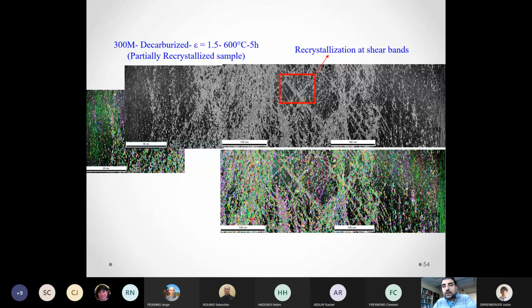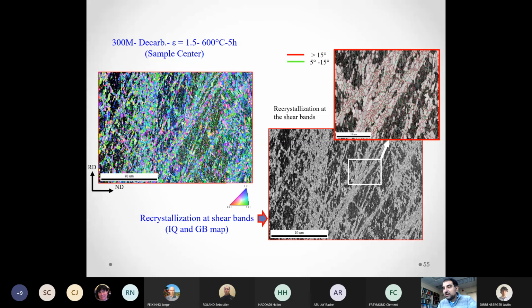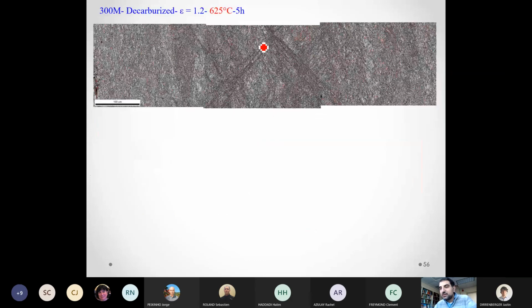When we increase the temperature and the time, we now begin to see recrystallization, and you see the recrystallization starts preferentially along those shear bands. So we're able to now take advantage of the shear bands that formed during deformation, the non-uniform deformation of the material, to create a non-uniform grain size or a mixed grain size distribution, where we have recrystallized grains along the shear bands and recovered grains between them. And if we're a little bit more patient, or if we go to a higher temperature, we can get complete recrystallization, as we see here.